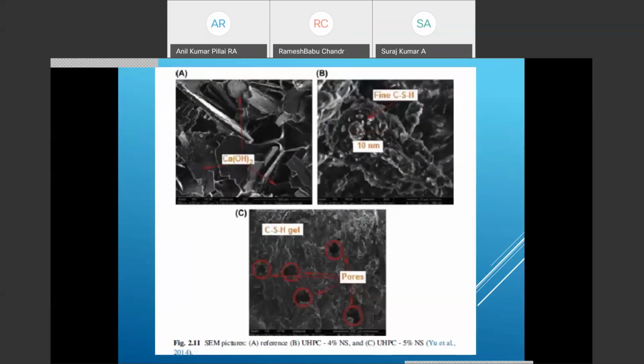the research. Here is some picture that is showing you calcium hydroxide flakes, and the second picture B shows you fine calcium silicate hydrate gel of dimension 10 nanometers, and the third picture shows you the reduced pores because of using 5% nanosilica, and it is an ultra high performance concrete.